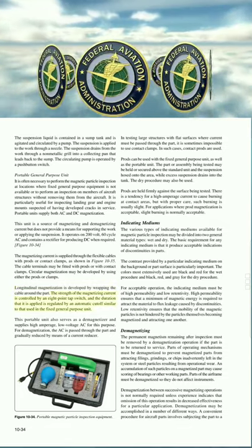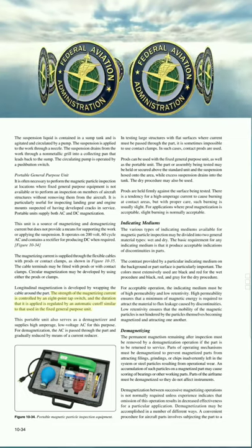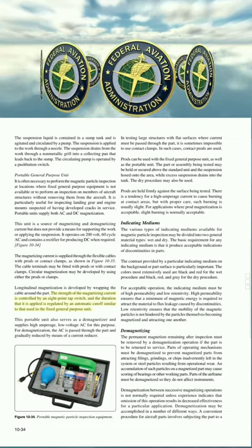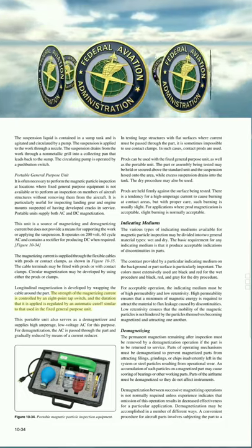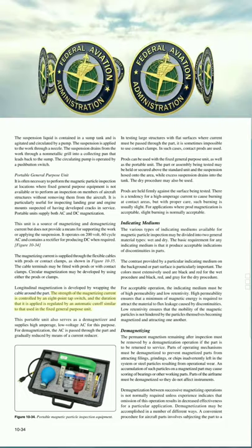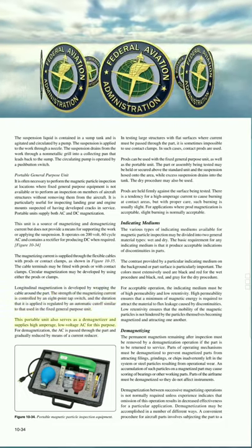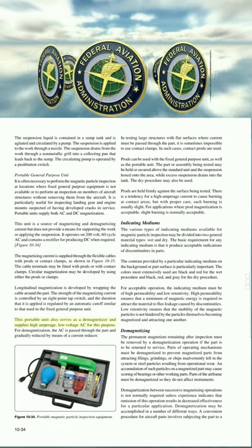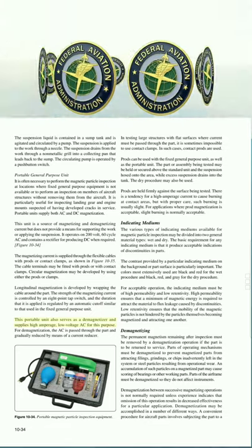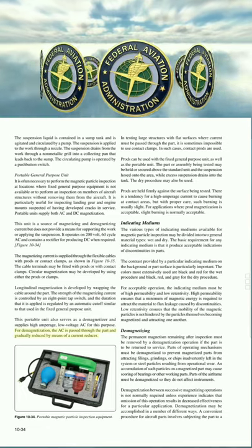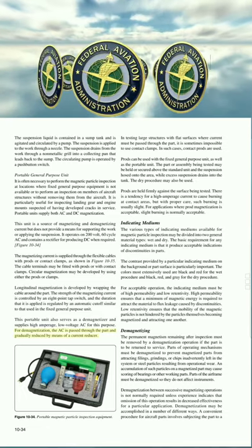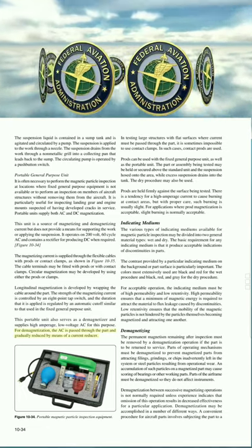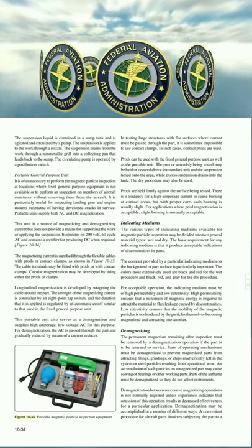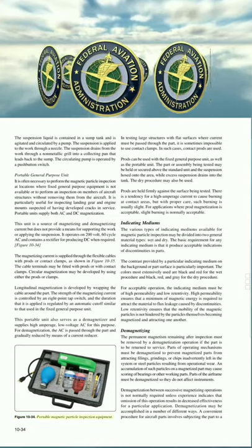The strength of the magnetizing current is controlled by an 8-point tap switch, and the duration that it is applied is regulated by an automatic cutoff similar to that used in the fixed general-purpose unit. This portable unit also serves as a demagnetizer and supplies high amperage, low voltage AC for this purpose. For demagnetization, the AC is passed through the part and gradually reduced by means of a current reducer. Figure 10-34. Portable magnetic particle inspection equipment.